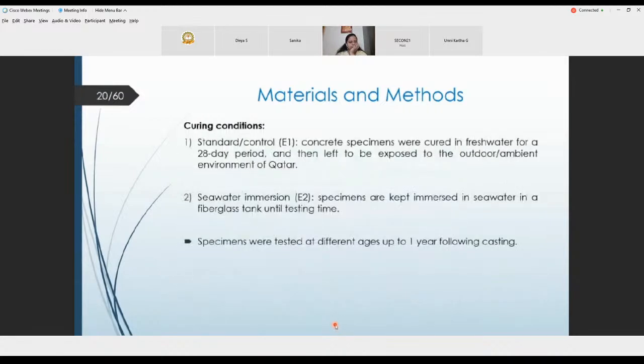The curing conditions also differ. We have standard curing conditions. We call it E1 in our study here, where concrete specimens were cured in fresh water for 28 days and then left to be exposed to the outdoor or ambient environment of Qatar.